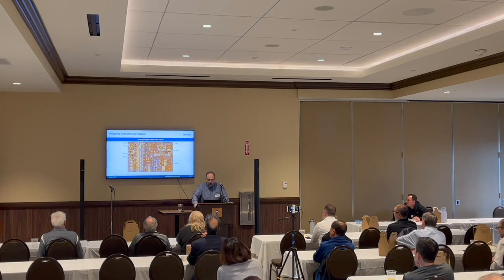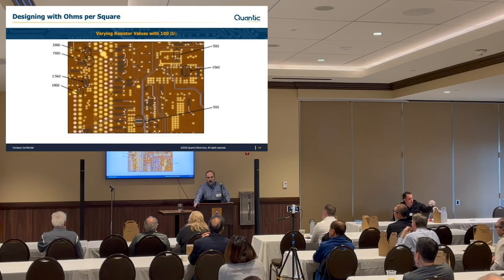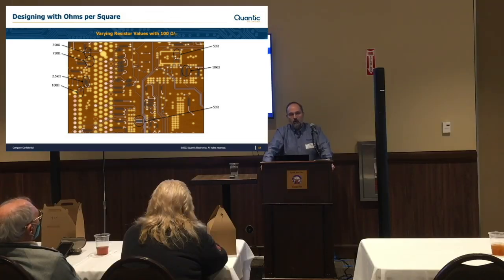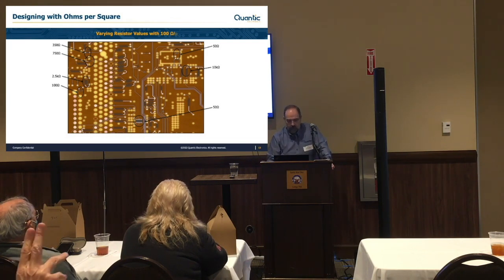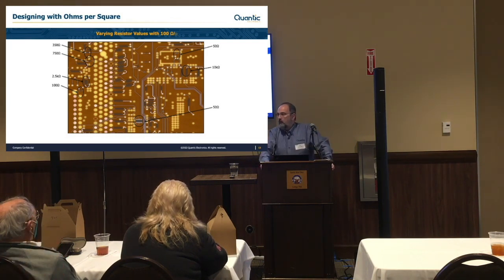Here's an example, and by doing that, you can use different types of patterns. You can use just a regular block, or let's say you want to have a real high ohmic value, you can use a serpentine pattern. So you basically can go like this and make a serpentine, and that will now give you a much higher ohmic value. And what's nice about that is, even using a 25 ohm material, you can go anywhere from a 25 ohm resistor all the way up to a 1,000 ohm resistor or more, depending on how you do the geometry. Okay? Does all this affect heat dissipation as far as like the serpentine or the thinner, the thicker?